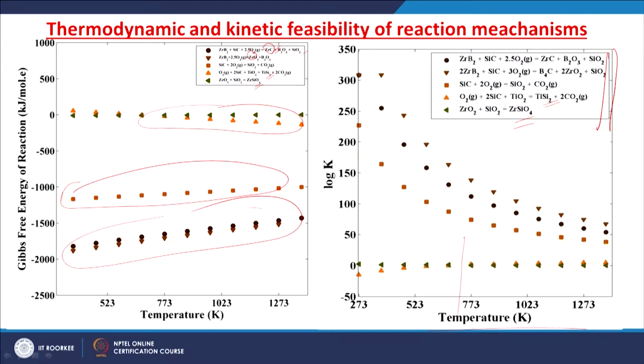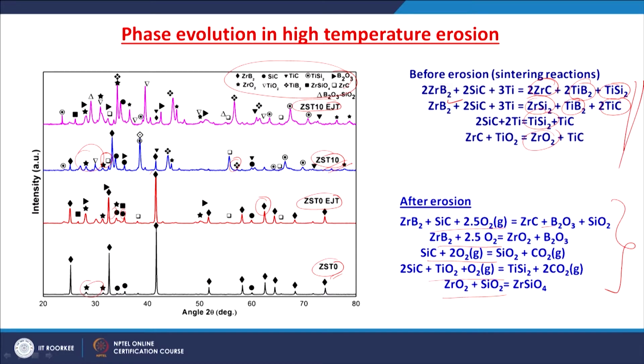So, we have certain zirconium carbide, boron oxide, silicon oxide, boron carbide, zirconium oxide, silicon oxide, titanium silicide, zirconium silicate, etc. So, we have several phases on the surface. One important observation is there is no titanium here. Even before starting the erosion, sintering itself resulted in certain compounds of titanium boride, titanium silicide, titanium carbide. We do not have any metallic titanium. That indicates that the titanium was consumed completely during sintering and formed different phases. Because of the formation of these hard phases, we have an improvement in the hardness and fracture toughness.